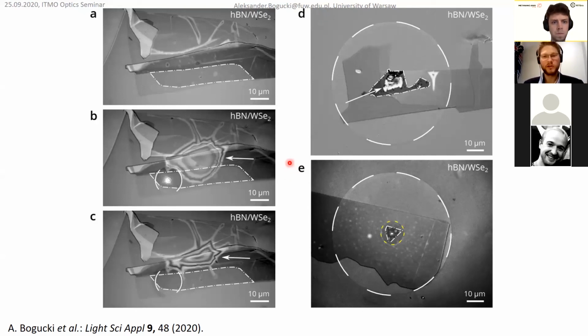Yes, exactly. We usually have a lot of samples in our drawers, because of the MBE laboratory. The standard procedure is that we take a very small piece of sample with quantum dots, which is already grown by MBE. Then we put a droplet of this photoresist on top of our sample, put it into the Nanoscribe writing machine, print, and develop in a solvent, which is PGMEA and isopropanol. Then when it's dried, we measure it. So this is the standard procedure.